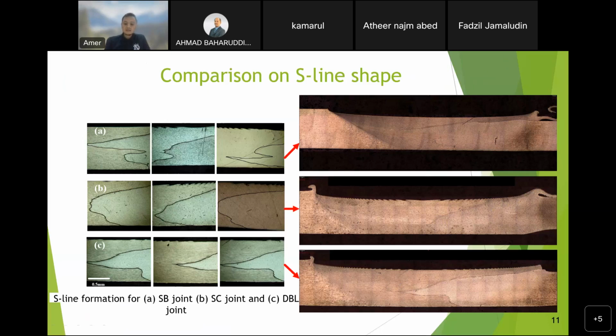So the tensile test revealed that the square butt joint has the lowest UTS value, and the double butt joint has the highest UTS value. This signifies that the shape and the length of the S-line profile influence the strength of the friction stir welding joint. The S-line shape is caused by the geometry configuration of the welding area, where each joint has a different surface area.